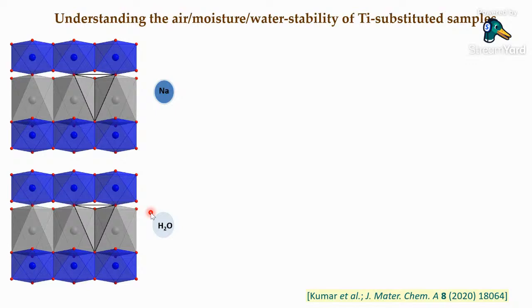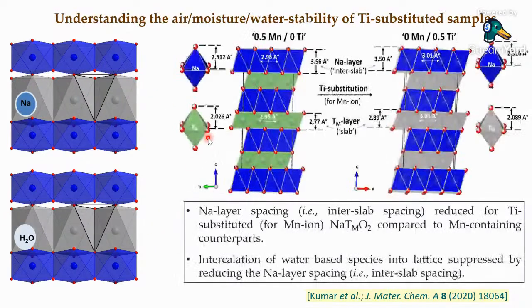Now, there are various reasons why titanium substitution may suppress the moisture uptake. So for trying to understand that, let us first see what happens when these layered transition metal oxides are exposed to moist air or water. The sodium ion is taken out, and the water goes in. Water based species go in, and they follow the same pathway. That is, if I again show this, it moves from octahedral site to tetrahedral site to octahedral site to tetrahedral site in the sodium layer. So spontaneous sodium extraction and water insertion takes place and follows the same pathway.